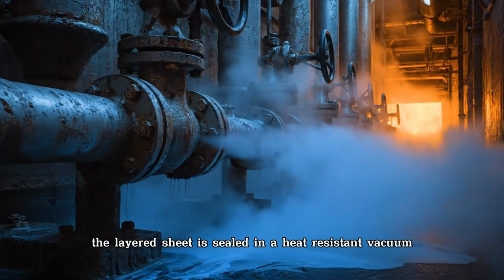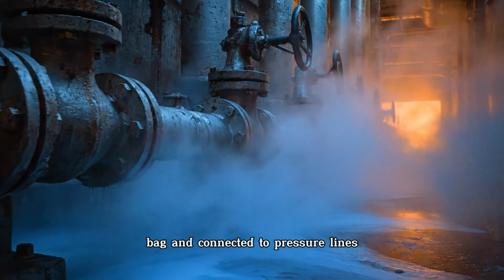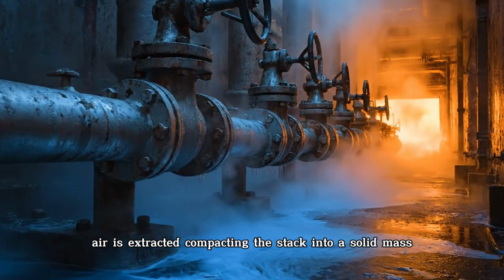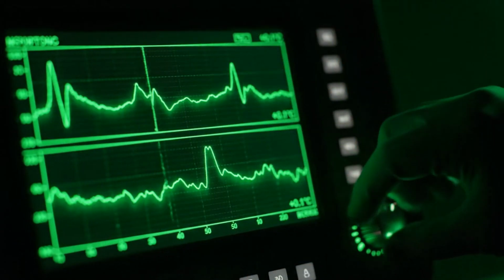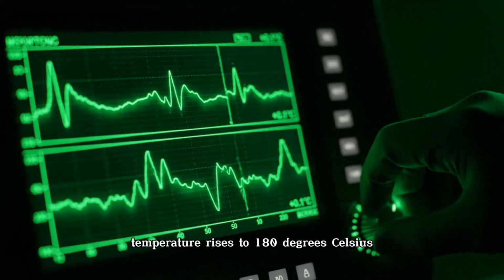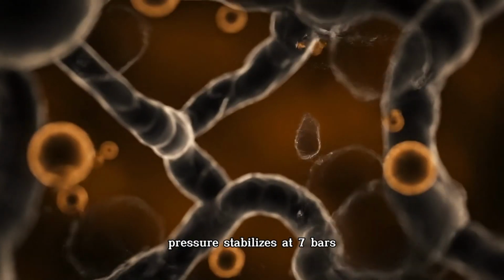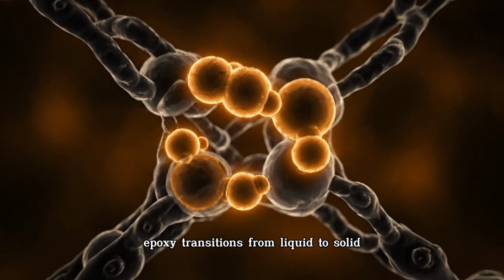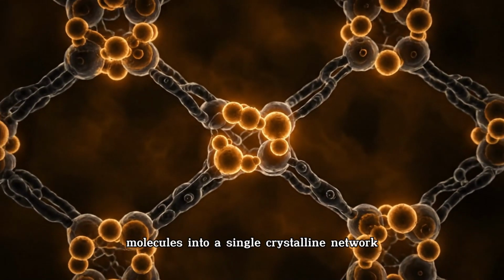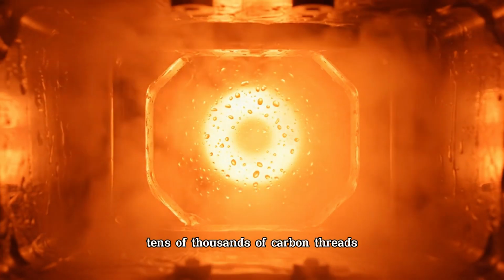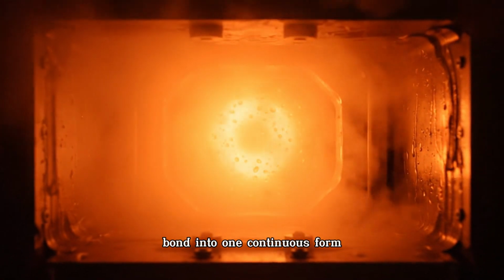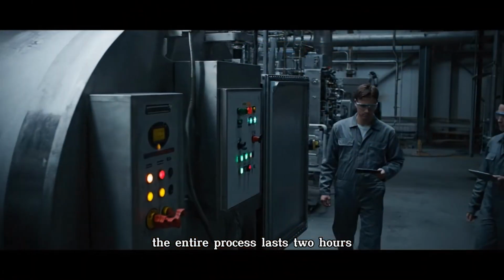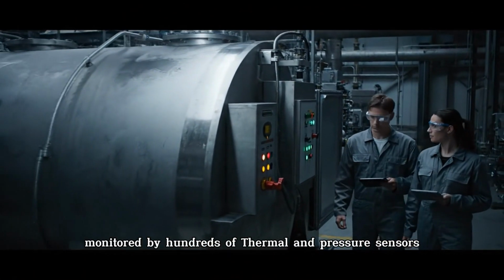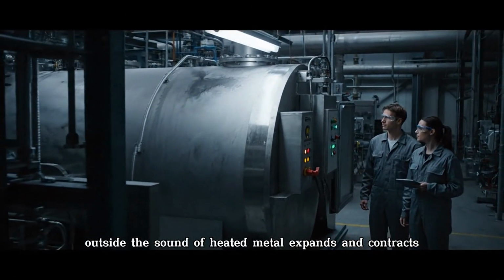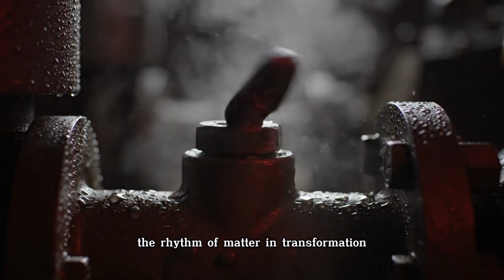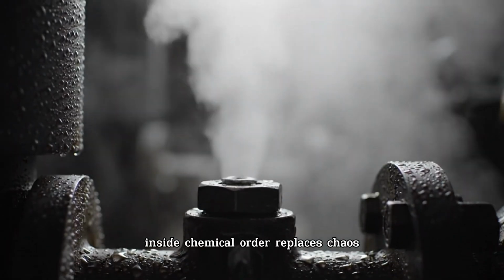The layered sheet is sealed in a heat-resistant vacuum bag and connected to pressure lines. Air is extracted, compacting the stack into a solid mass. Inside the autoclave, temperature rises to 180 degrees Celsius. Pressure stabilizes at 7 bars. In this controlled chamber, epoxy transitions from liquid to solid, turning random molecules into a single crystalline network. Tens of thousands of carbon threads bond into one continuous form. The entire process lasts 2 hours, monitored by hundreds of thermal and pressure sensors. Outside, the sound of heated metal expands and contracts, the rhythm of matter in transformation. Inside, chemical order replaces chaos.